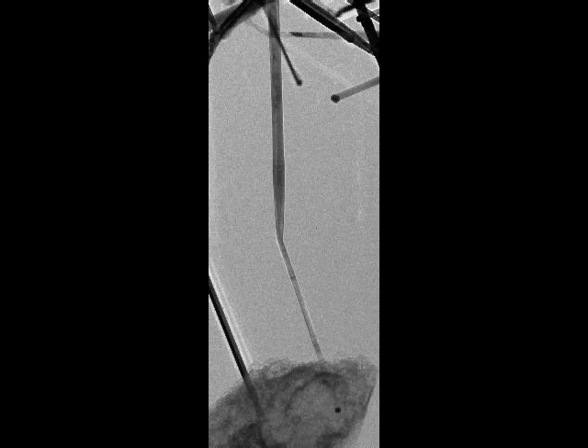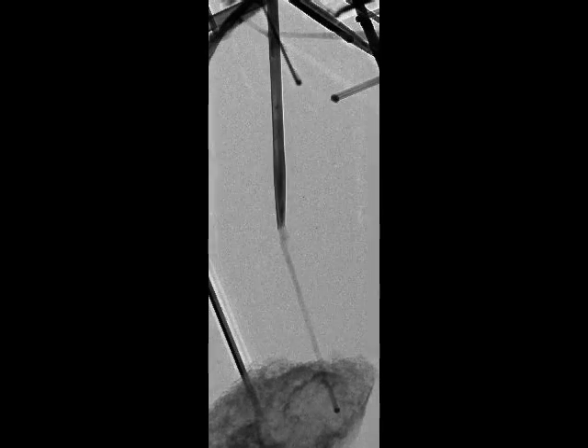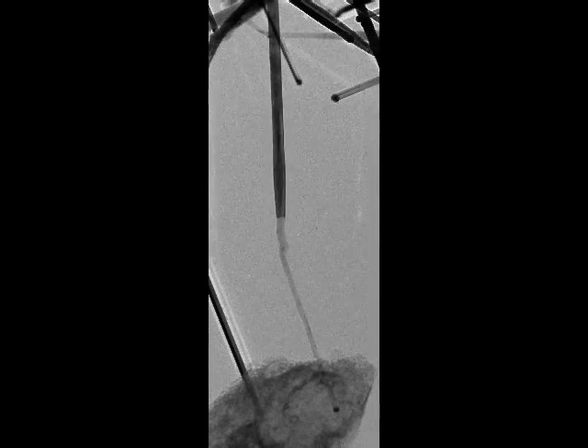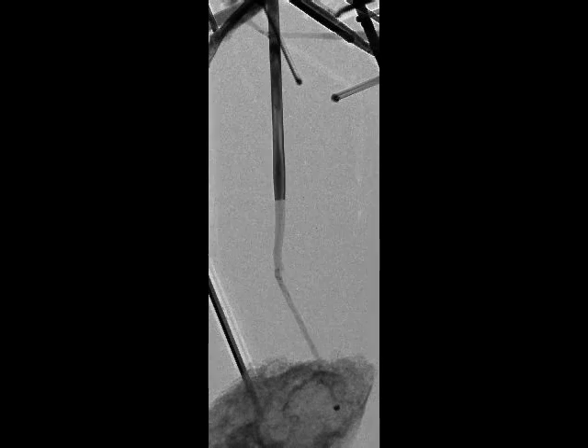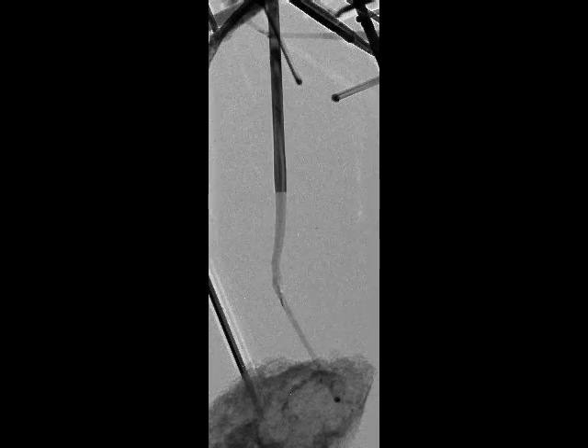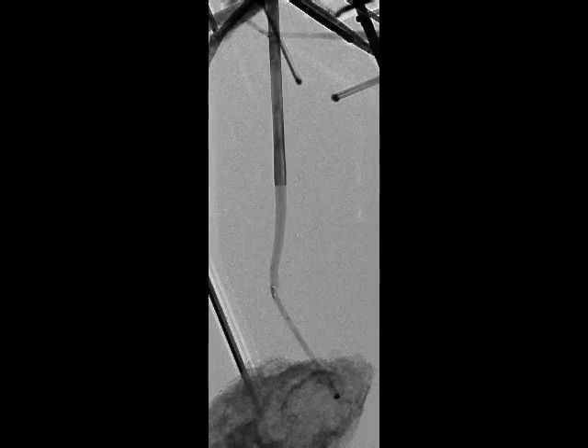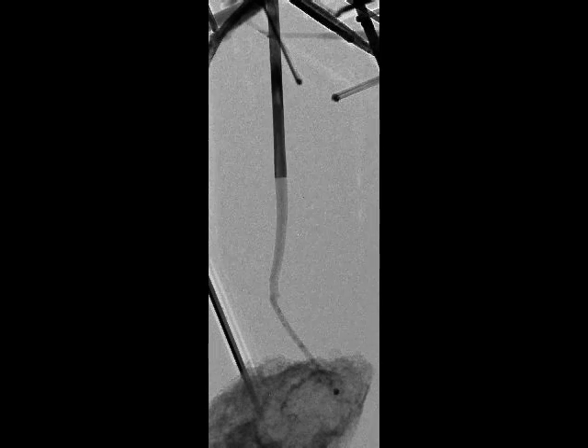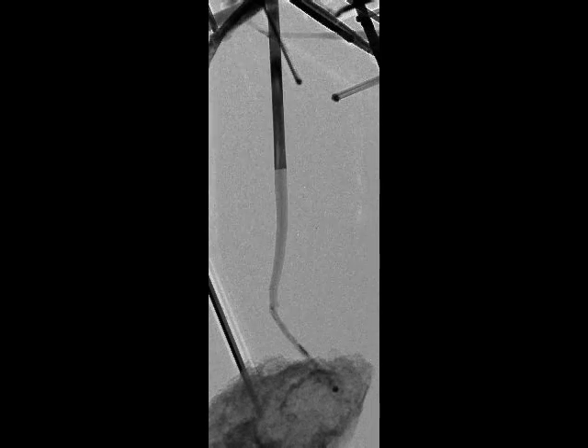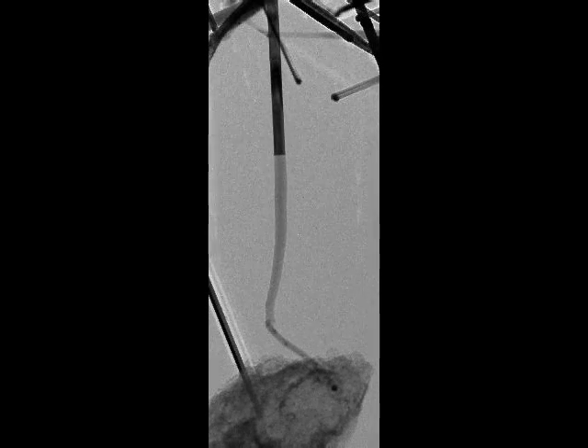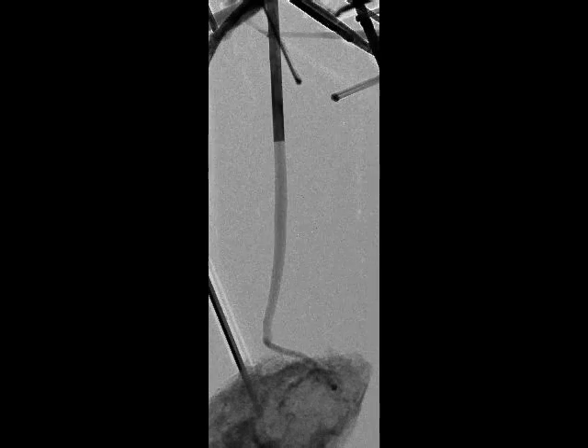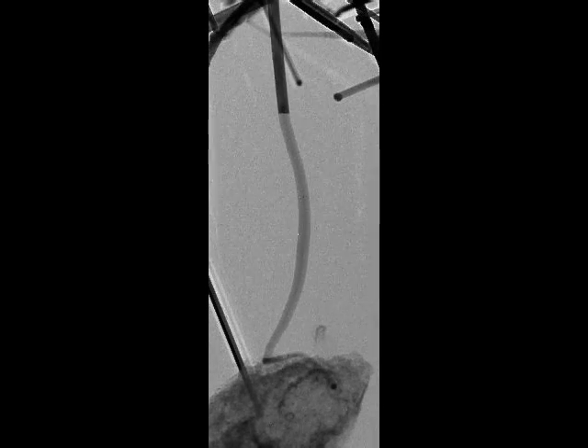Now, when we look at the second video, where we have a single wire that has a small narrower region at its tip, which is silicon, but then the rest of the wire is a germanium-silicon core-shell wire. As lithium ions reach the second segment, which is the longest one, a germanium-silicon core-shell wire, you start to observe that the lighter contrast proceeds axially into the wire. It's not from the surface.